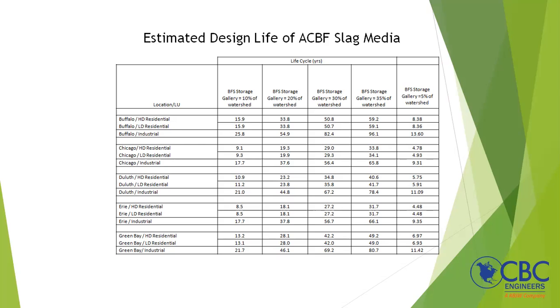Now understand, all of these numbers are based upon 1 milligram per liter, and in the urban environment, it's pretty difficult to get up around 0.5 milligrams per liter, because that's really what you're looking at from leaf degeneration or vegetative phosphorus from vegetative runoff or fertilizers. So you're rarely going to see 1 milligram per liter, which is essentially what these numbers are based upon. And the other thing in the real environment is you don't get a constant 1 milligram per liter flow of phosphorus every time it rains. You may get 0.2, you may get 0.01. I mean, the variables are so dramatic and usually very low that my opinion is these numbers are extremely conservative. And so when we talk in terms of maybe a 25-year longevity, it really might be more like 50 years of longevity.